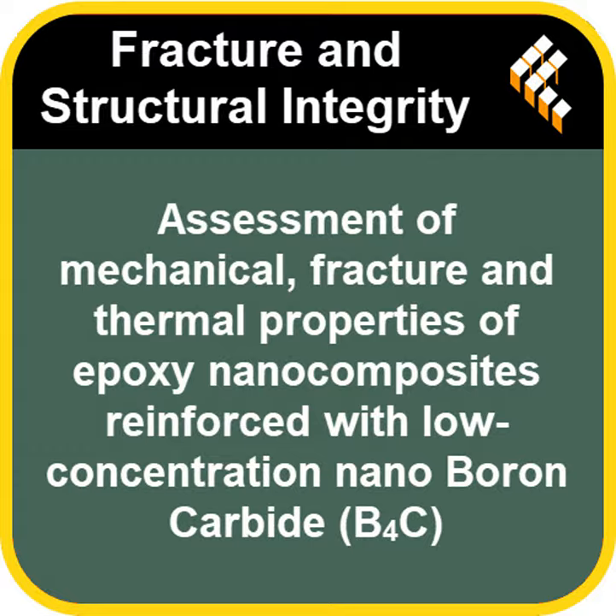Okay, so they're hunting for the biggest bang for the buck, basically. Maximum performance improvement with the absolute minimum amount of this B4C added. Did they find it? What's the big takeaway, the aha moment? Oh, they definitely found something significant. The main headline is that these incredibly small additions worked wonders. This research shows they got a 71% boost in tensile strength, and almost a 70% increase, 69.7% to be exact, in fracture toughness. So the epoxy became stronger, more stable, and much, much harder to crack, all without adding much filler at all. Wow, okay, that's impressive.